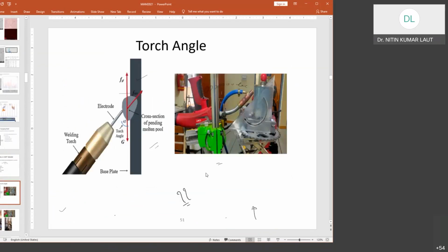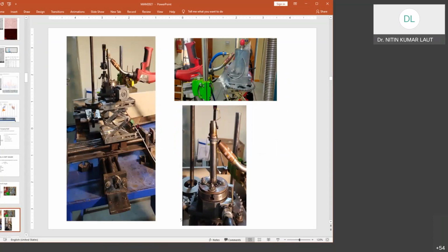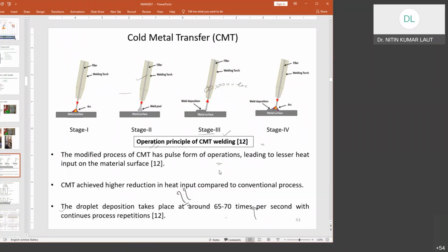Fine, I think I have to restrict myself, as these are all current researches which are going on, so I won't discuss. Just to recap what we discussed earlier, through this slide we'll go through the recap. We have a process which is used in additive manufacturing, that is cold metal transfer, which uses the filler wire to generate the arc, and in the weld pool it generates the droplets, and these droplets get deposited here, and this process continues because the wire is being moved inside the torch, and this is all electrically controlled using pulse forms, and as per this pulse formation they control the droplet feed or formation of the droplets.